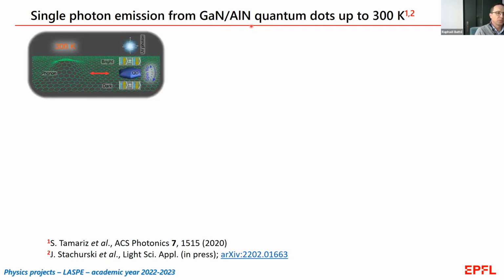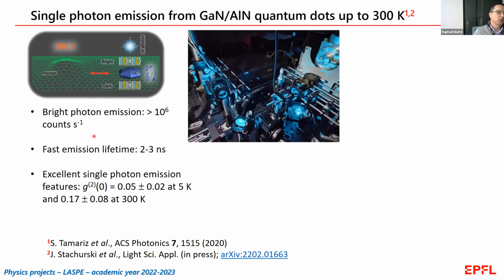The next project deals with the investigation of single photon emission originating from quantum nanostructures up to room temperature. Recently, we reported on single photon emission from gallium nitride dots embedded in an aluminum nitride matrix up to room temperature. And for such an entity, we could demonstrate a bright photon emission, a fast emission lifetime on the order of a few nanoseconds, as well as excellent single photon emission features.